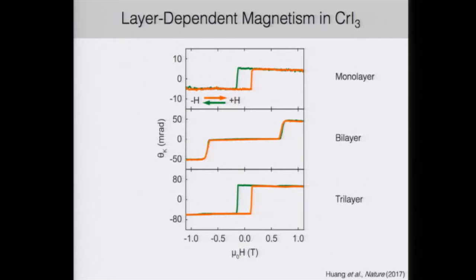So the magnetic anisotropy in chromium iodide comes from the iodine ions because they have strong spin-orbit coupling. Oh, so that's what makes it. So that's what gives rise to the strong anisotropy. Yeah, so it depends on the material.